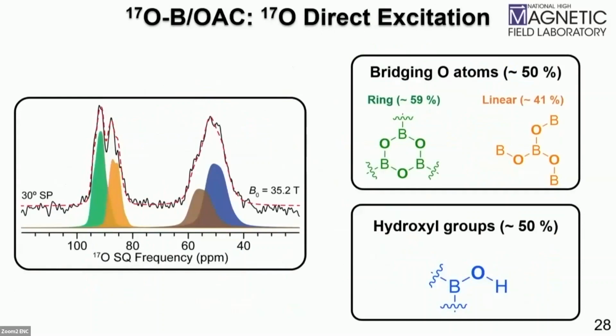So now with complete oxygen signal assignment on hand, what we can see from our ultra high field oxygen NMR spectrum is that about 50% of the oxygen are hydroxyl groups. So this is showing that this oxide layer is extremely hydroxyl dense. We also see that there's about a 60-40 ratio of ring type to linear borate species, showing that both are also very abundant.